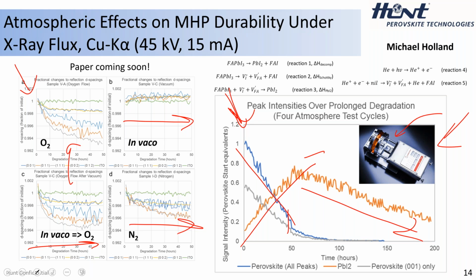So what do we think is happening? So starting here, reactions 4 and 5, this is kind of the supposition that the hν here, being X-ray photons, are creating some sort of a plasma. Create free electrons near the surface that can react. Nil is the initial perovskite, unaffected perovskite. This electron can react with the surface in some way to create iodide and FA vacancies, reform the helium, making a catalytic reaction, but this results in the loss of FAI. So the vacancies represent the new material, the new perovskite material that now contains these vacancies, and the FAI is a species that has left the system.